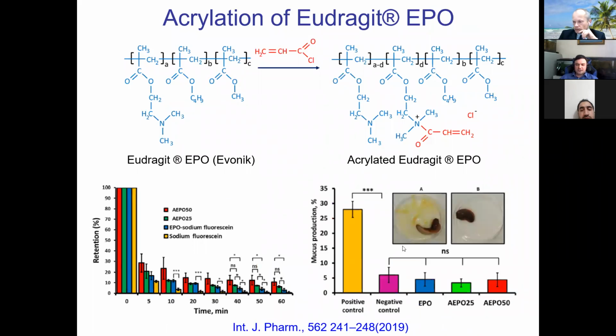Then, because I already said that pharmaceutical scientists like easy systems, we tried to convert the same chemistry into an easy system. We took a conventional copolymer, which is a pharmaceutical copolymer produced by Evonik, called Eudragit. They have the same groups as in the nanogels before, and we decided to try this reaction to modify it by attaching the acryloyl chloride. Again, the same story, we have improved mucoadhesiveness, but we also started looking at toxicological assays to characterize the irritation properties of these polymers, because mucosal surfaces are quite gentle, so you could irritate them.